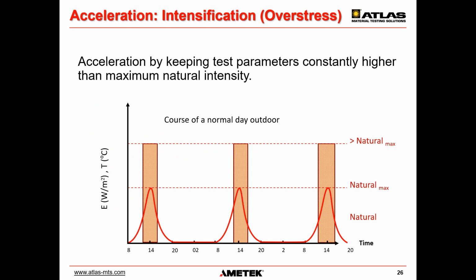It's through overstress. That is increasing a stress parameter such as solar irradiance, in this case here, or temperature, to higher levels than what would occur outdoors. What this means is that rather than conducting a test at near maximum or maximum levels, you run it higher than maximum levels. One example of this type of acceleration would be the Fresnel reflecting devices in Phoenix, Arizona. We call them EMMAQUA, where we use highly reflective mirrors to focus several sun equivalents onto one single target board, at least in the UV and low wavelength visible range. And this is a very established method and works quite well.